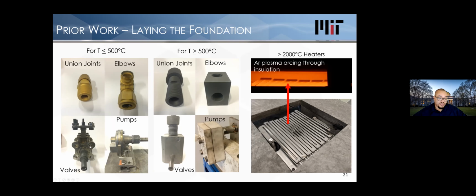These are old pumps and valves that we made that were actually all stainless steel, and we coated them with chromium nitride, and they work quite fine. No issues with any corrosion with liquid tin. When we want to go to the very high temperatures, we then switch to all ceramic or graphite systems. This, for example, on the right here, this is an aluminum nitride pump. This was the first pump we made. And we have, essentially, considerable experience now working on technologies in this temperature range.